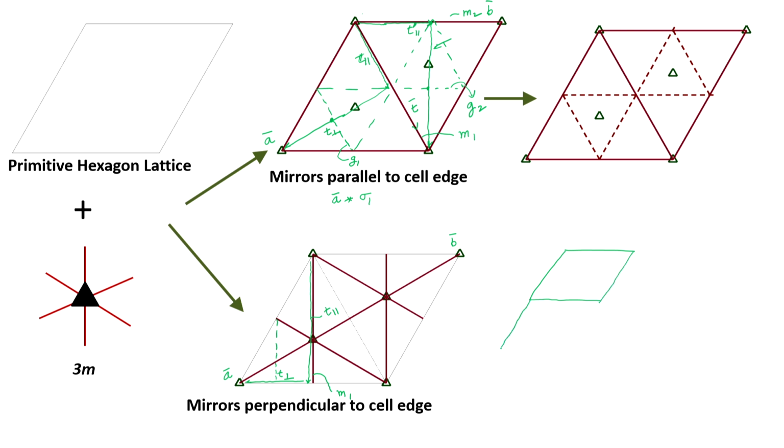Let us draw two adjacent hexagonal cells. My T parallel component is this, but it does not end at a lattice point. If I extend this further, it will end up at this lattice point. So, it starts with a lattice point of one corner of one cell, ends up at a lattice point in the adjacent unit cell corner. And you can see clearly again that T parallel is exactly half the lattice translation which joins one lattice point to another lattice point. Hence, let us call this glide G1.